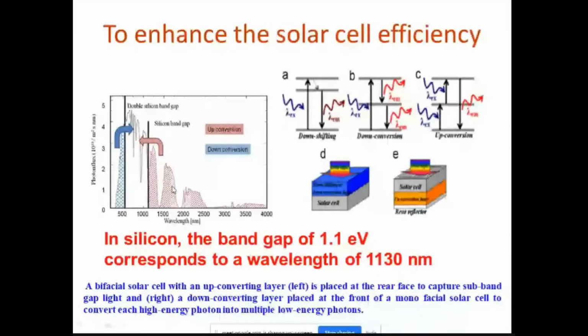And now there is a rare earth ion layer. What it will do is lower energy will be converted to higher energy, which is exactly equivalent to 1130 nanometers, a process called up conversion. And similarly, this is the higher energy which can be converted into lower energy, which is called down conversion. So these are all rare earth based layers. Those layers will convert high energy and low energy to the energy that exactly matches the silicon solar cell. Previously, only this energy was converted into electrical signal. Now you are able to convert even the low energy and high energy in a solar cell. So the rare earth based materials can also be used to enhance the solar energy.